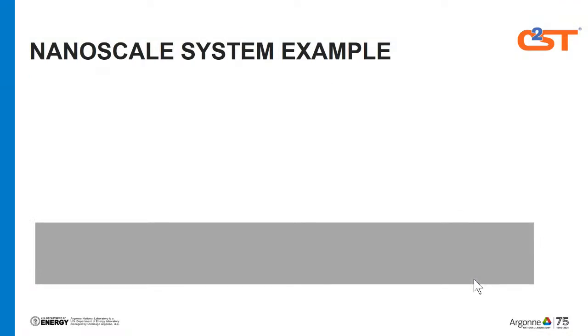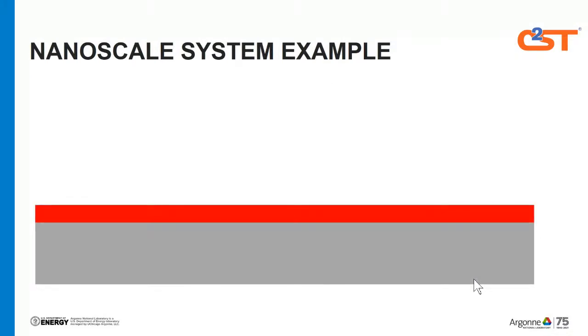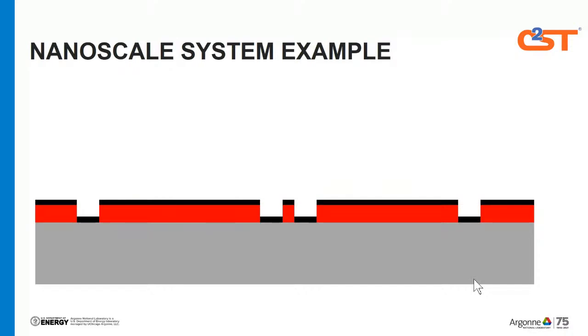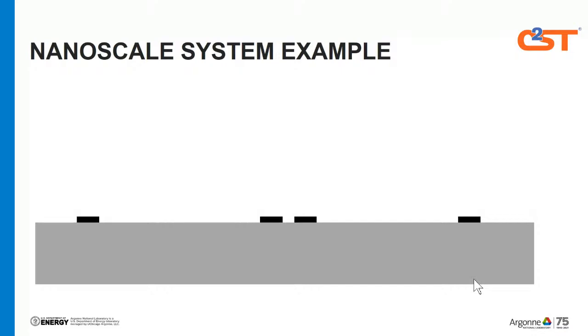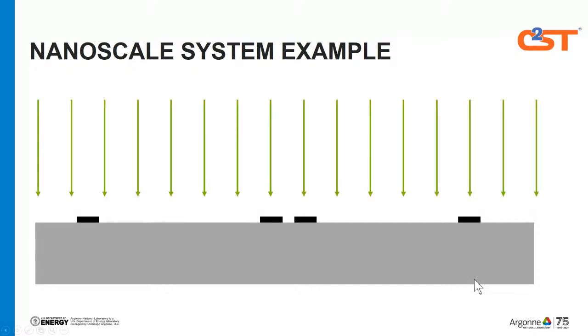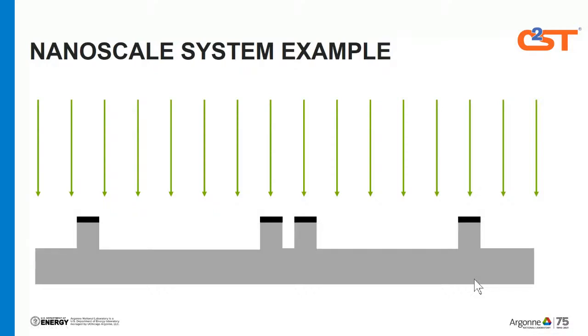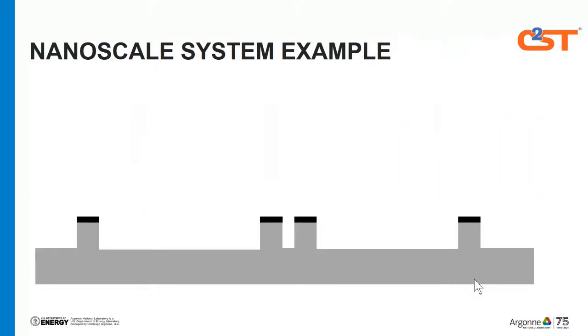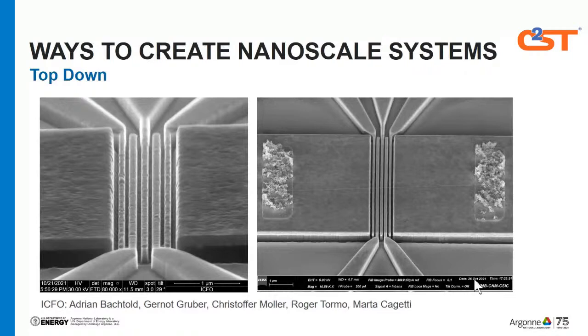As a brief overview, we start with the substrate. We use, again, a polymer that's sensitive to electrons. We make a pattern, and in this case we're going to deposit a metal, platinum. We lift off the rest on top of the resist. We use a reactive ion etch, a plasma process, to etch away the silicon underneath, and we end up with a structure that looks like this.